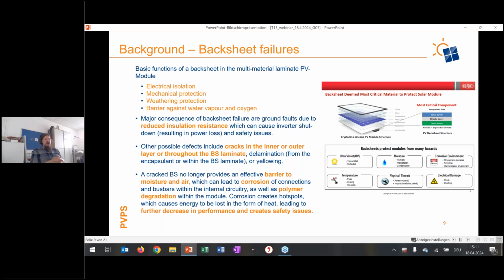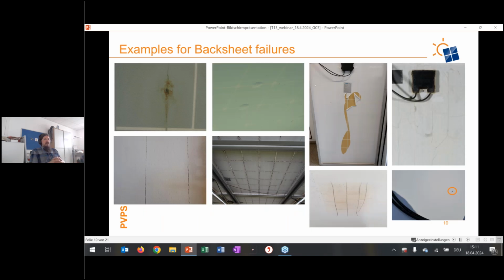And in the longer term, this can cause corrosion of the interconnections and bus bars. It can accelerate polymer degradation within the PV module. Further on, hotspots can be created, overall leading to a further decrease in performance and more safety issues. So these are just some examples of backsheet failures. You see various types of cracks, delaminations, blisters, or here in the down right case, this discoloration. This is because of a hotspot cell where we locally have a much higher temperature.